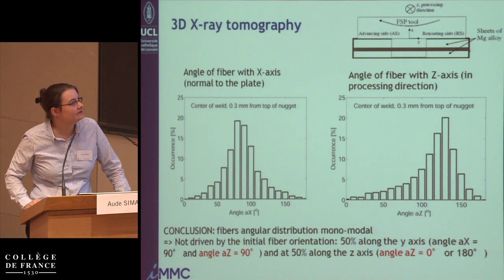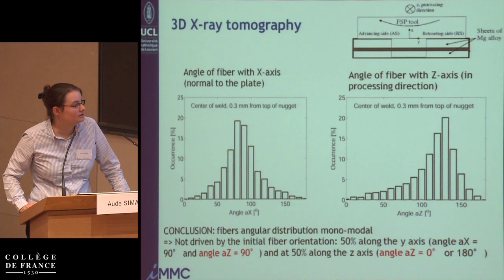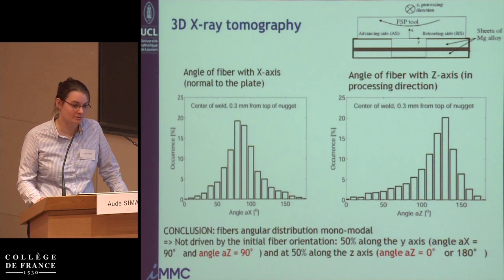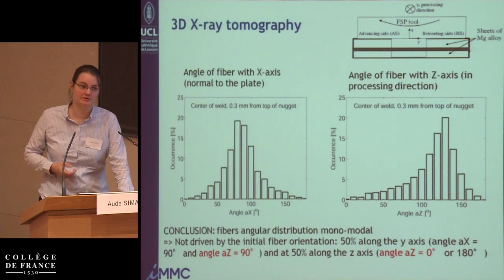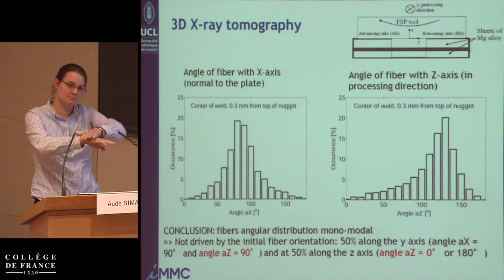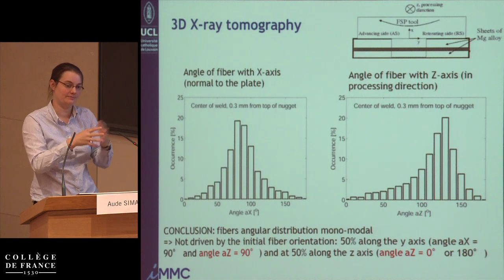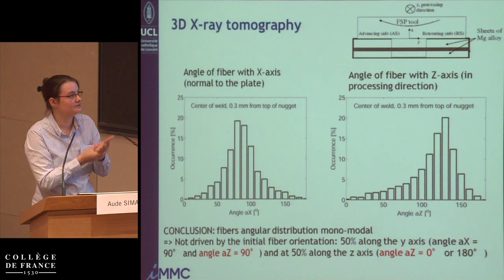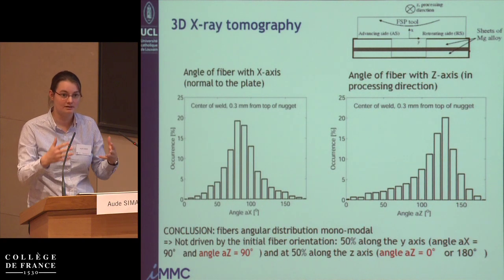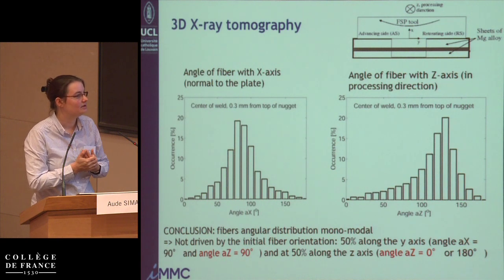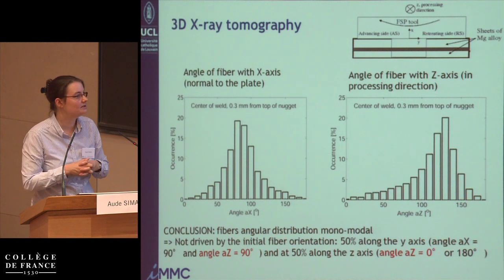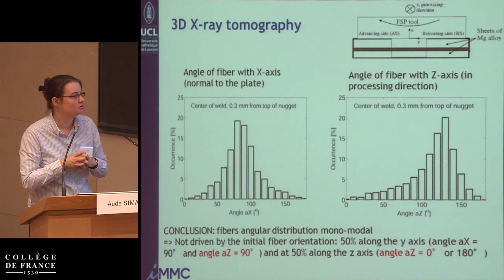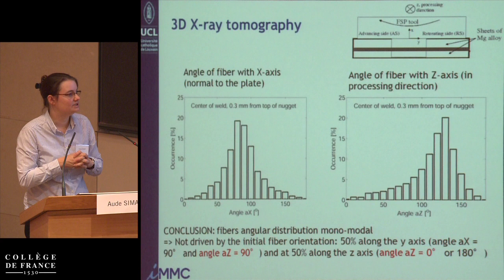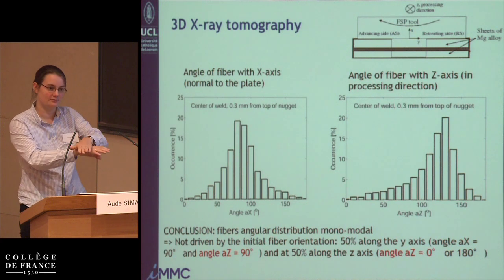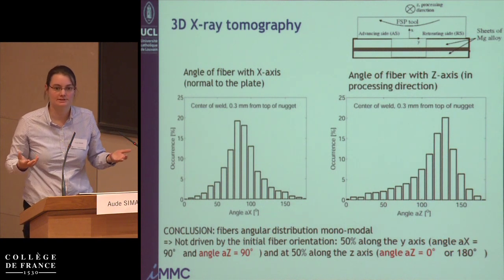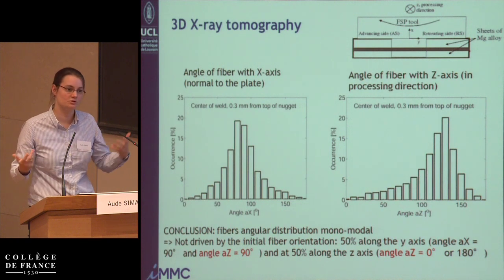And here is an interesting thing that we found. At the very beginning, when you start making these materials, you start with a carbon fabric, and the carbon fabric has fibers in both directions. They are perpendicular, and so they are made like this. And what we observed by the X-ray tomography, we could analyze all the angles of these particles, and what we saw is actually that the distribution of angles of these particles is very much centered over one value, so a monomodal distribution, compared to the situation where, starting from things that are perpendicular, you would expect to have a bimodal distribution. So that shows that the process has a huge impact on the distribution of the particles, but also on their angular orientation.